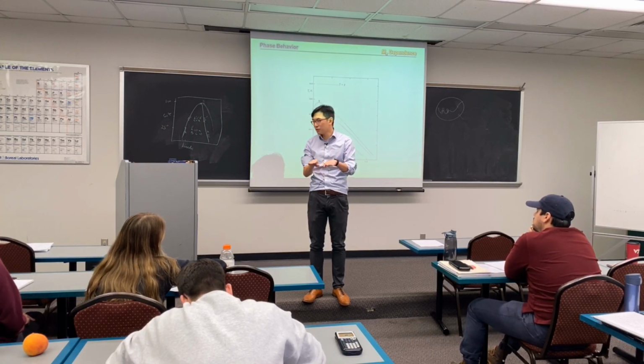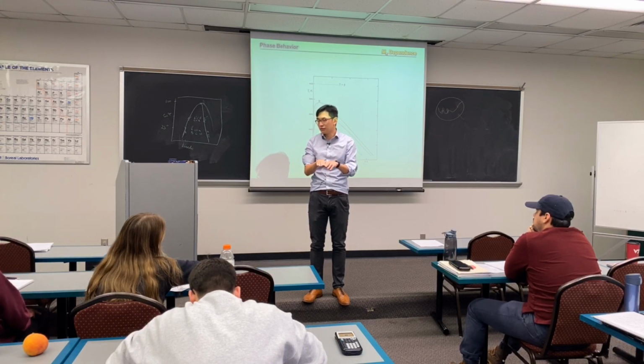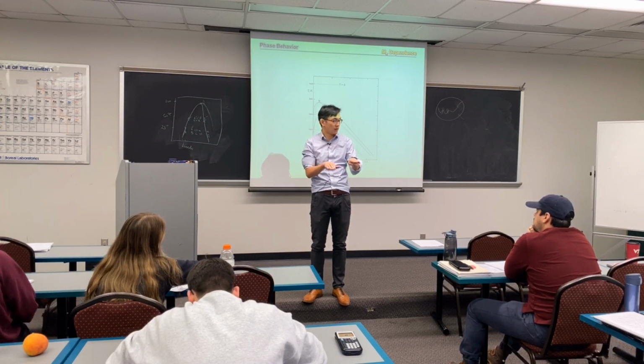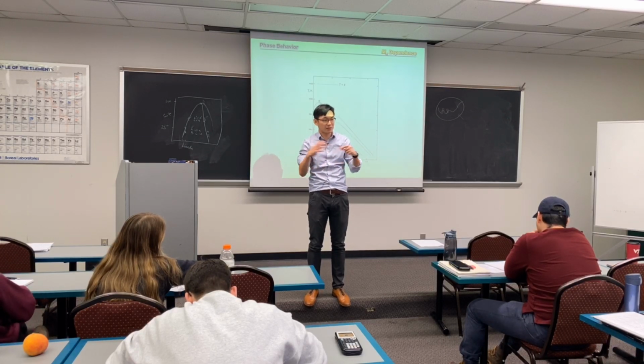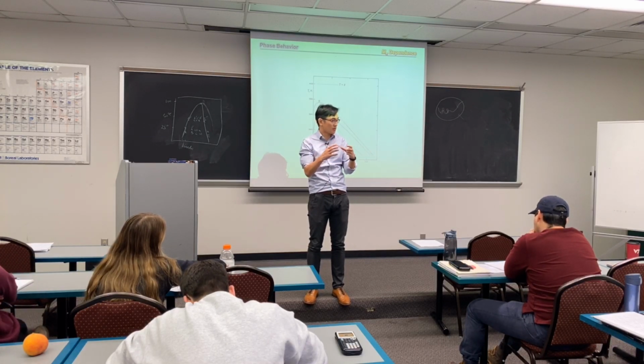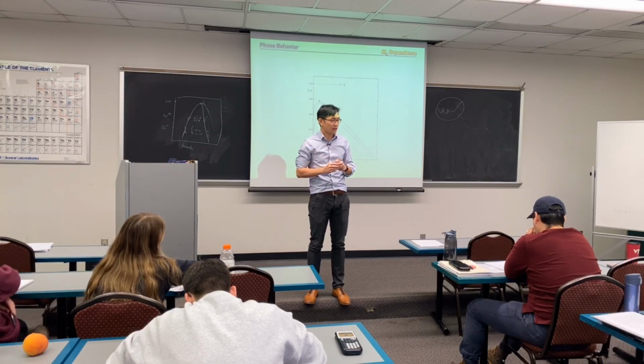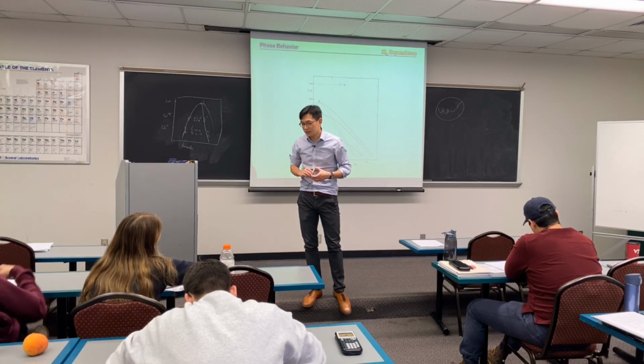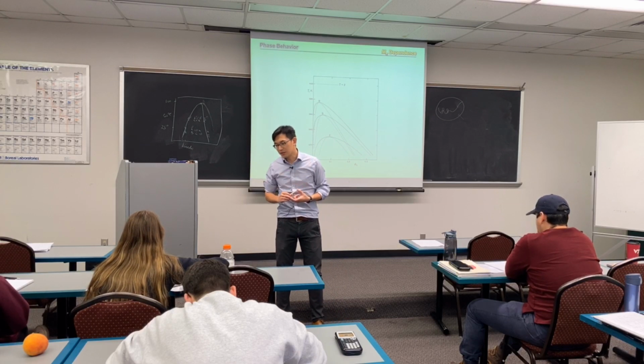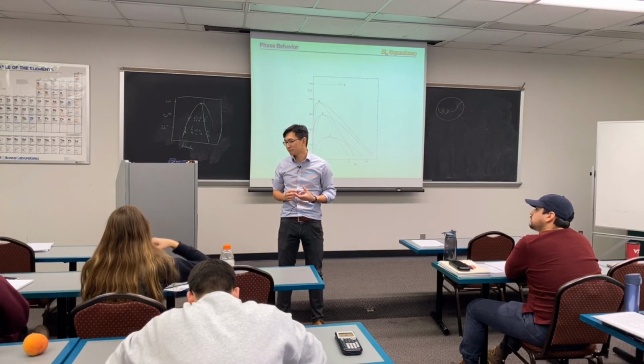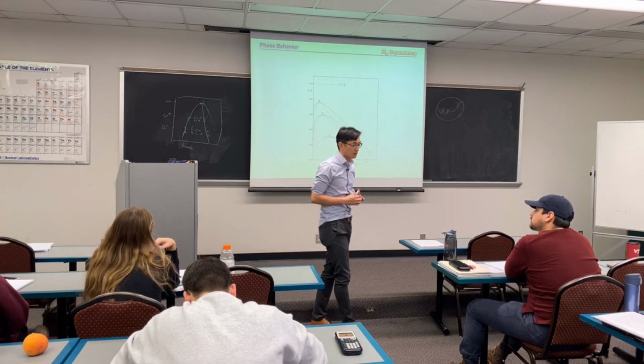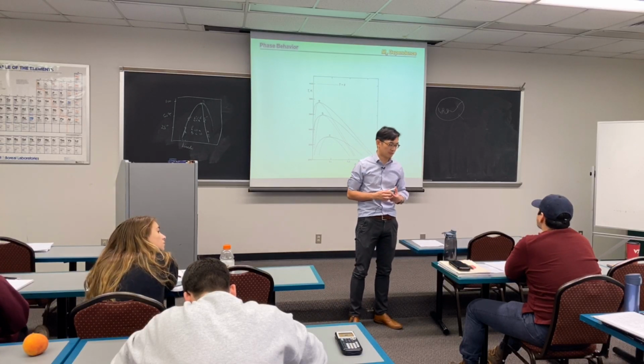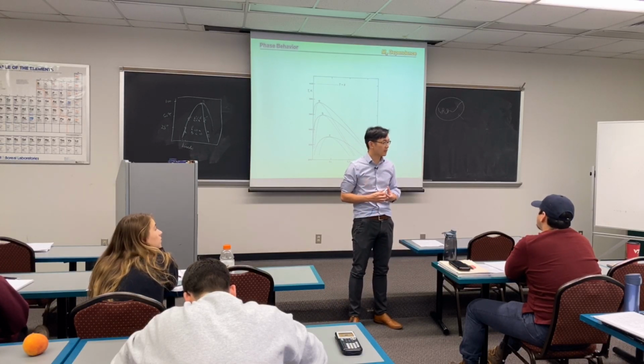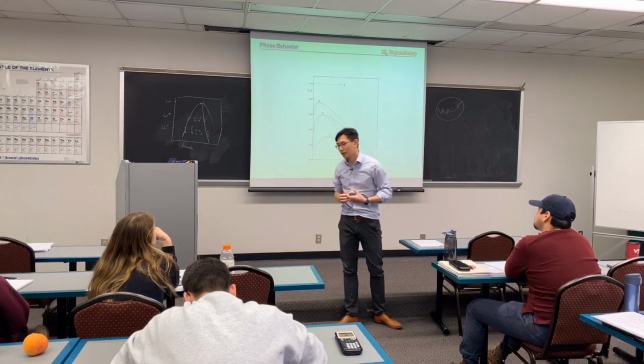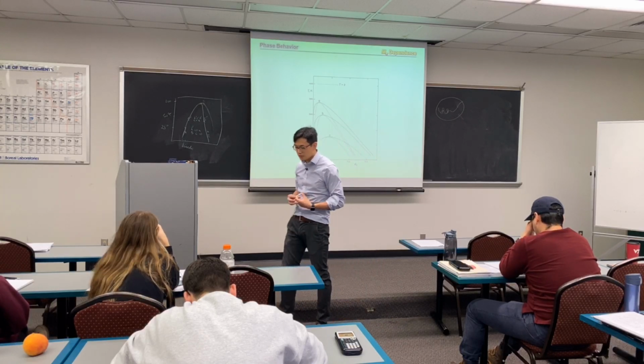Okay, I'm not going to go into too much detail, but if you calculate the interaction between the polymer and polymer versus the entropy loss due to the chain expansion, or you think about the chain as an entropic spring, you can easily obtain that in a good solvent, your RG will depend on the molecular weight to the power of 3/5. Okay, that is briefly discussed in the textbooks in the last chapter.